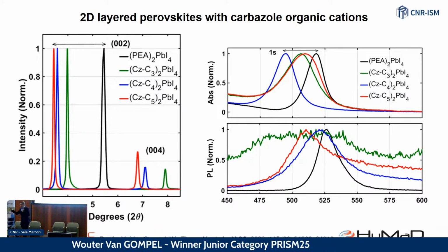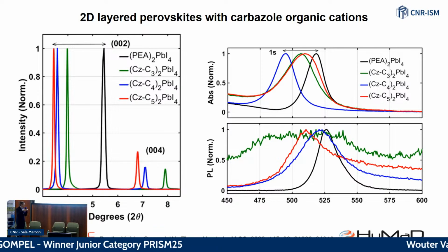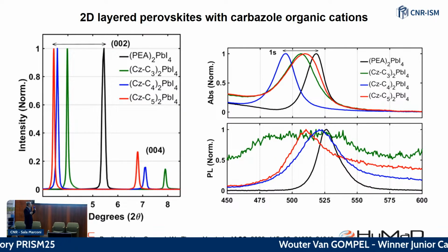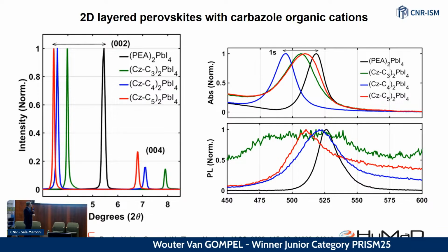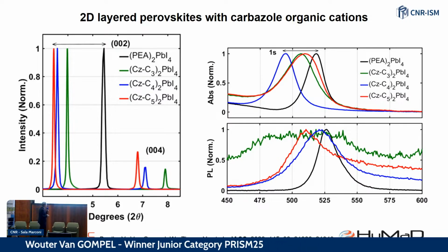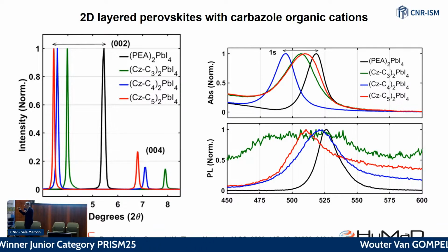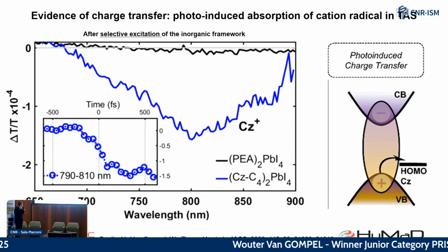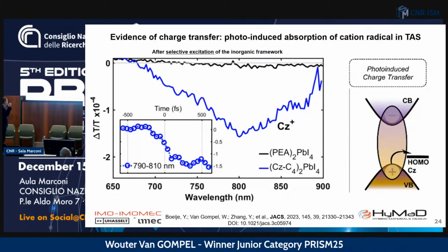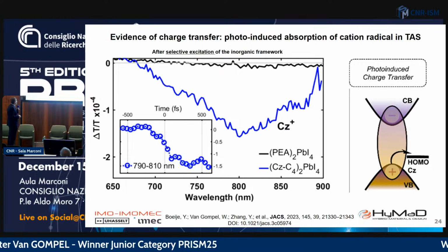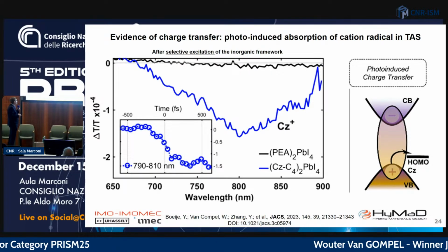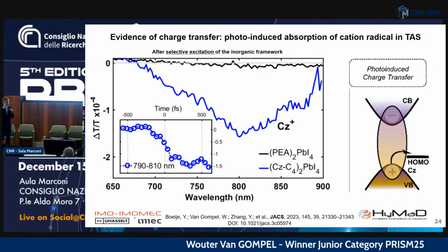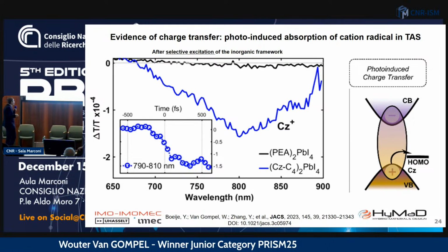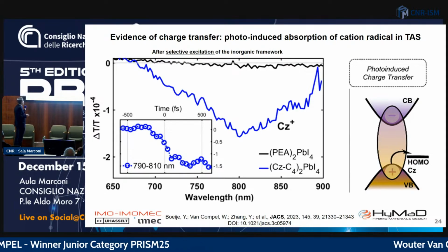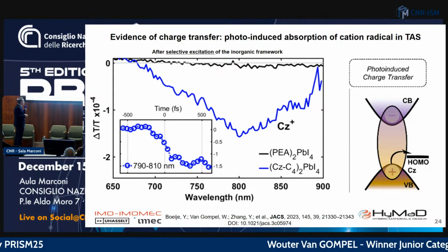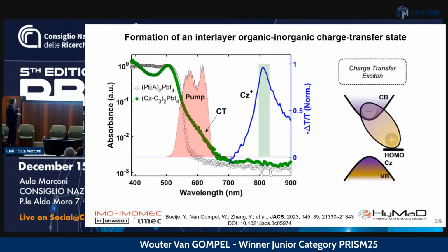Of course, if you get charge transfer from the organic to the inorganic, or from the inorganic to the organic, you separate the electron and the hole, and they can no longer recombine. So you do not get emission from the recombination. This quenching of the photoluminescence is a good signature for the presence of charge transfer in these materials. Together with the people in Cambridge, we did a detailed spectroscopic study, femtosecond transient absorption spectroscopy, and there we see a photo-induced absorption peak of the carbazole cation radical, which is a signature of the fact that this charge transfer has occurred. This direct proof was the first time that it was shown in the literature.